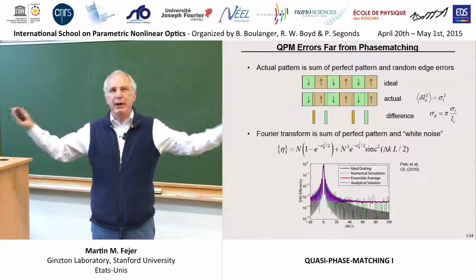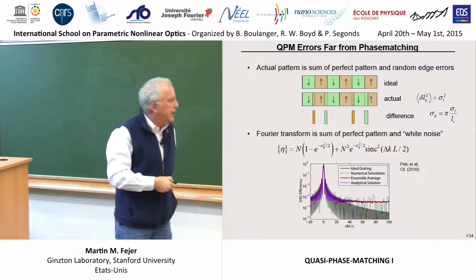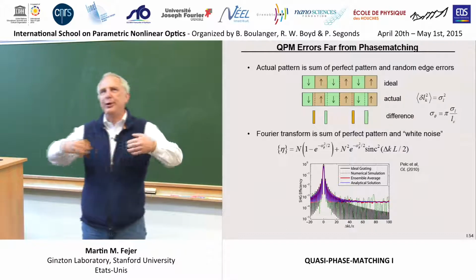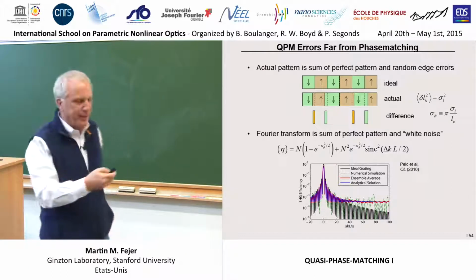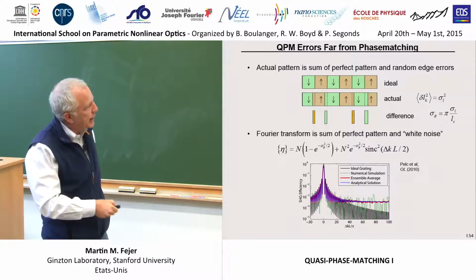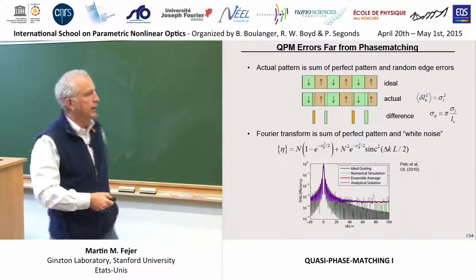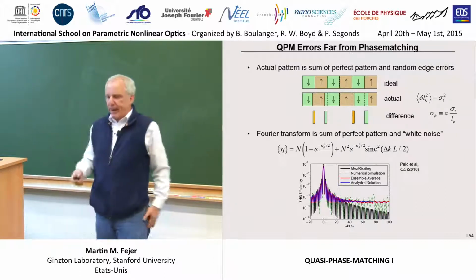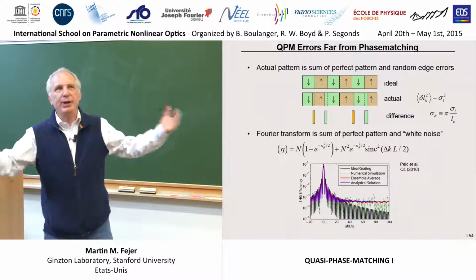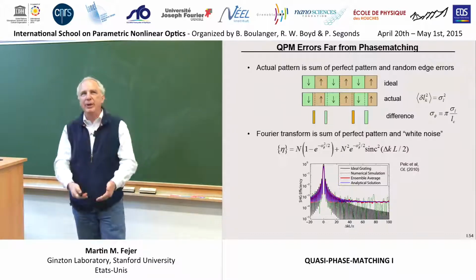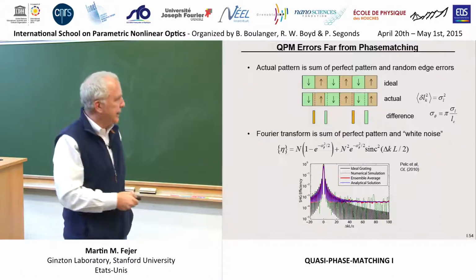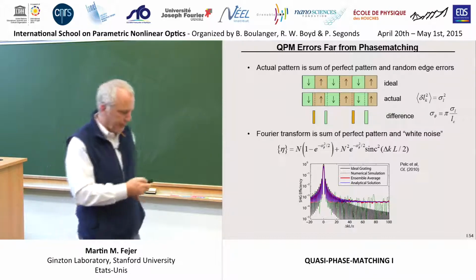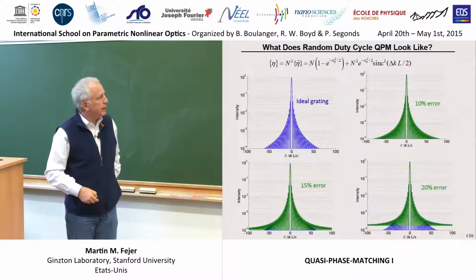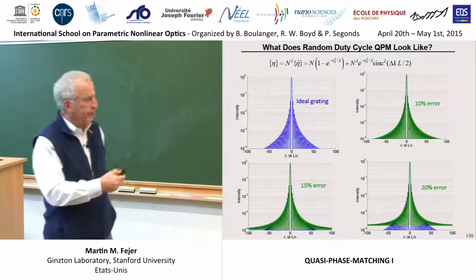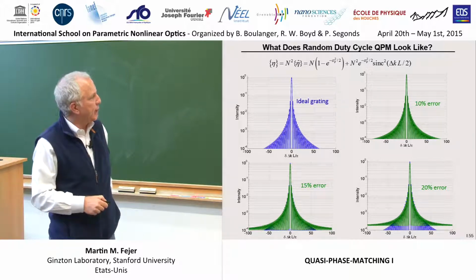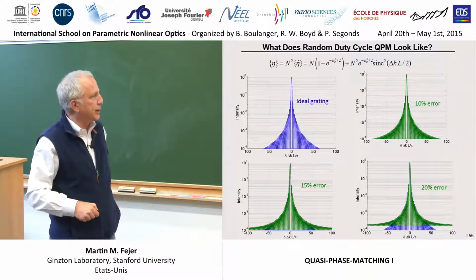And that gives you all these parasitic colors in your OPOs. And as we'll see, it can lead to parametric fluorescence where you aren't supposed to have any because it's badly phase mismatched by the ideal structure. But this pedestal here can phase match processes that aren't supposed to happen. So when you're sensitive to things that are 10 orders of magnitude down from the peak conversion, which you are if you're counting photons, this pedestal can be quite important. So this is just a cleaner plot of an ideal grating, a grating with 10% error, 15% random duty cycle errors, and 20%.